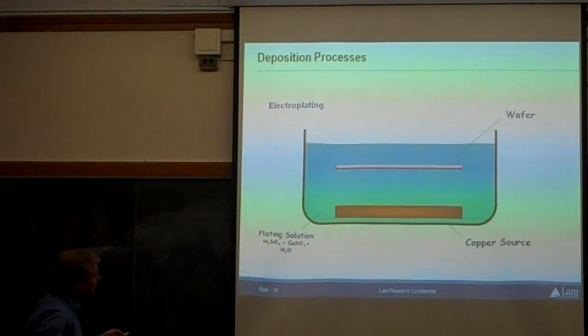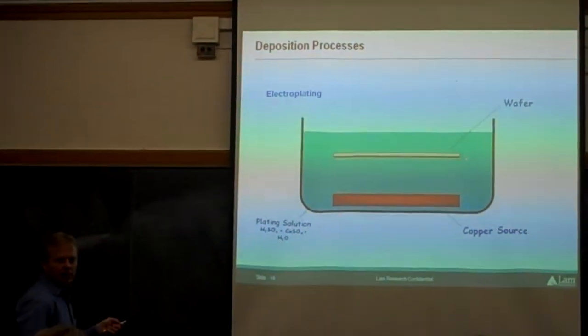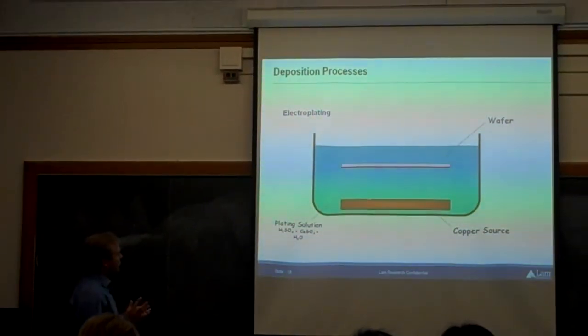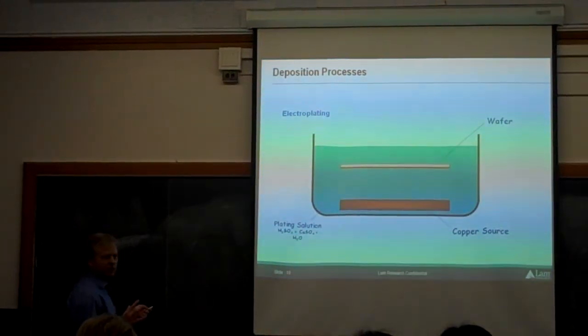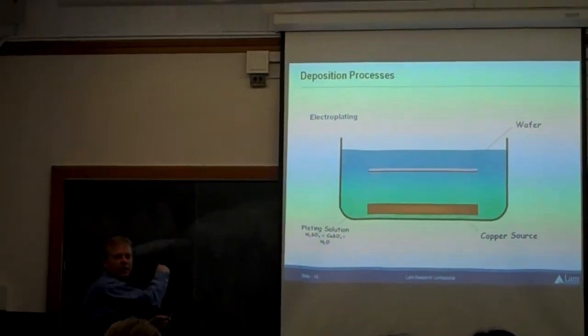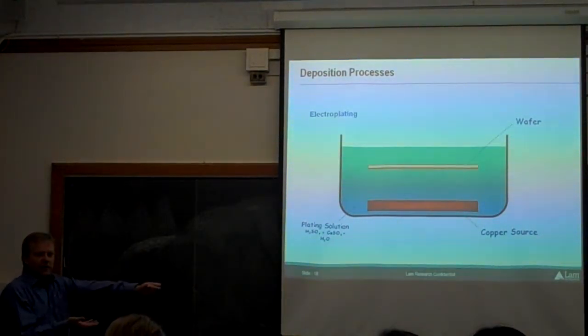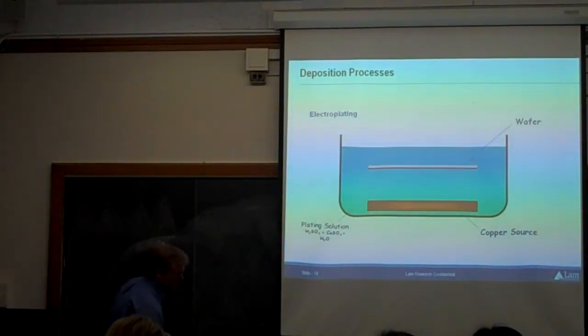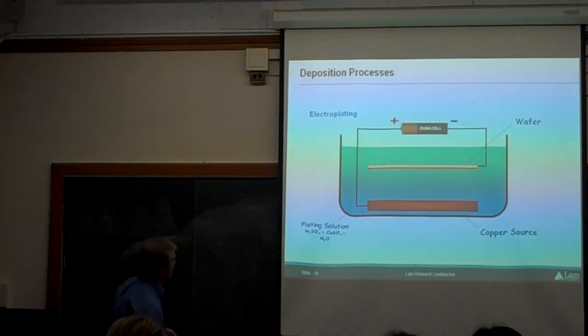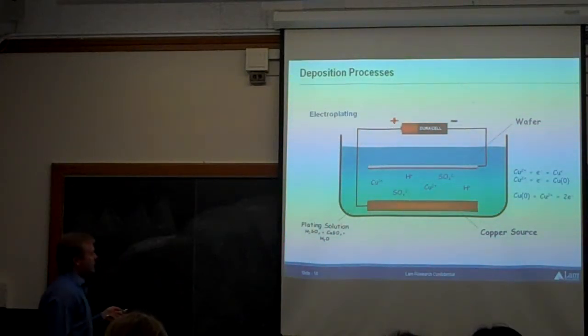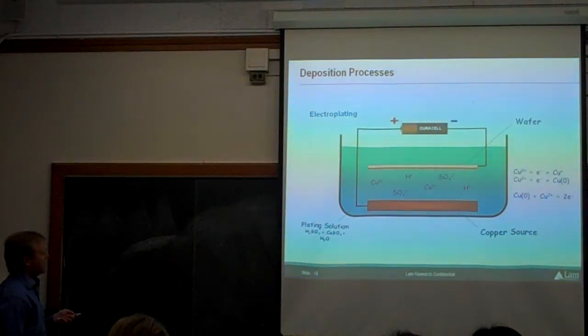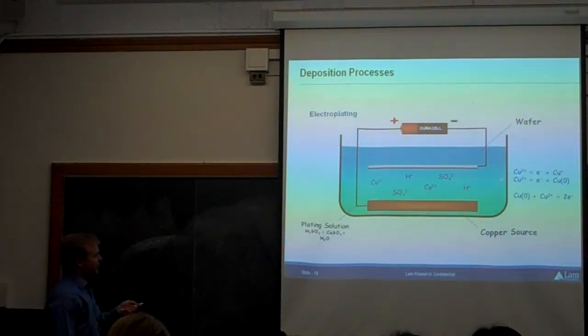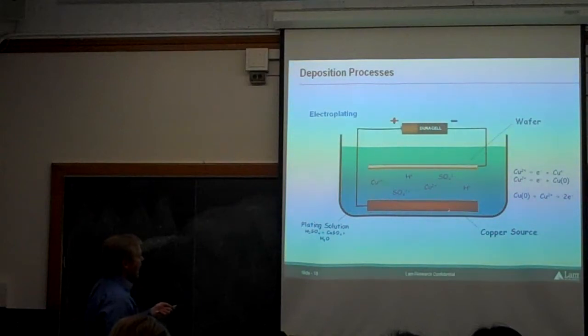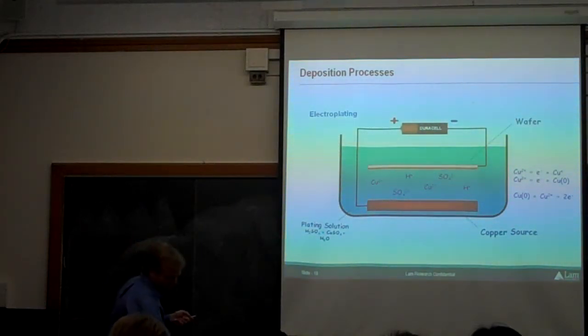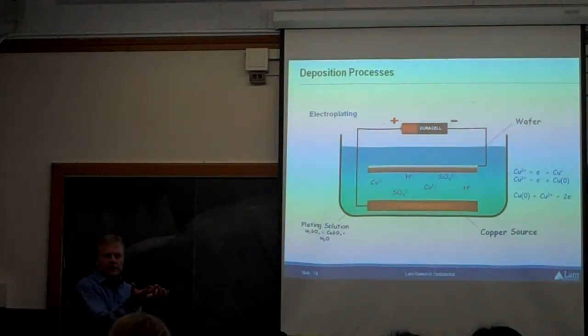And you notice there's actually a copper seed layer on here. This reaction won't work unless this is a conductive surface. So we use that PVD process I showed you before to put down that first layer of copper, and we put it in this electroplating bath, and you hook up your Duracell battery, and you'll just get a standard electrochemical reaction right here. And what happens is the copper will then migrate from the anode to the cathode, and I plate the copper.